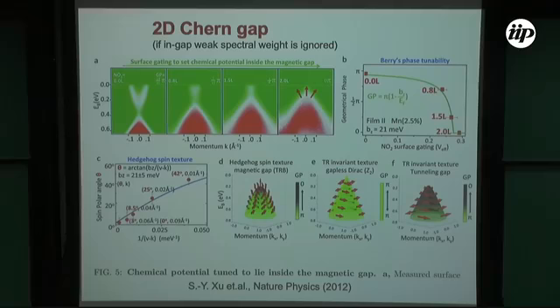So then we did a lot of systematics, because in a thin film there could also be a tunneling gap, with the two surfaces talking to each other, and that could be a gap. Then we can measure the spin texture and figure out what is the signature of spin texture disruption when the gap is due to tunneling, or when the gap is due to magnetism. So what we find is that when the gap is due to magnetism, if you place your chemical potential here, there's a net moment on the surface. So this is what we call hedgehog spin texture.